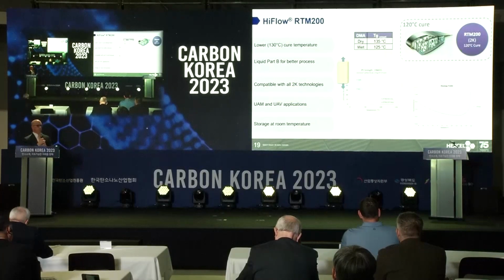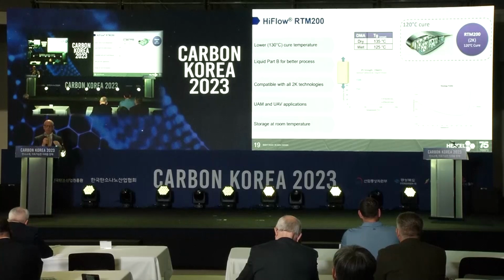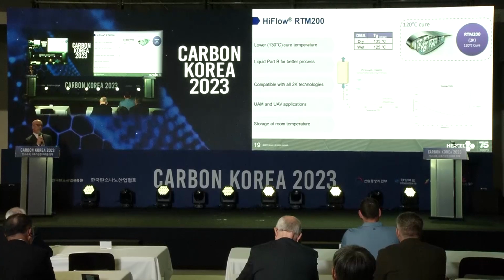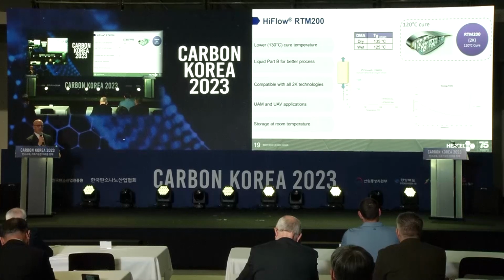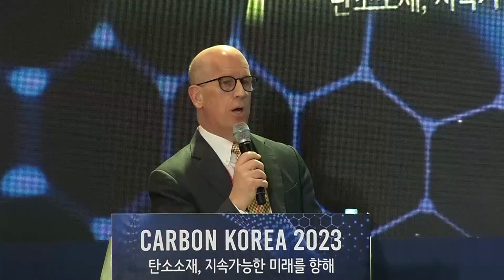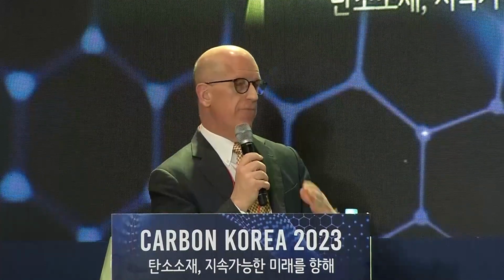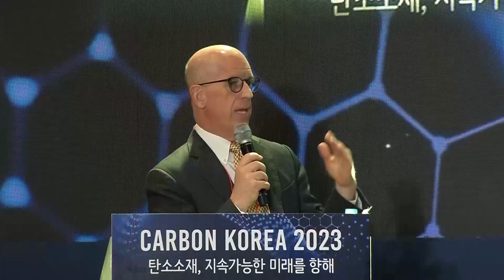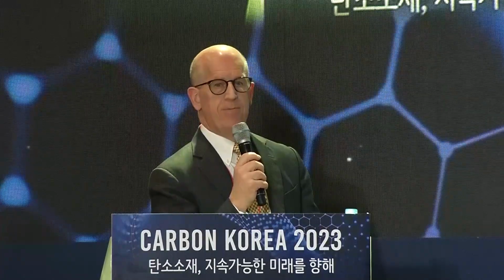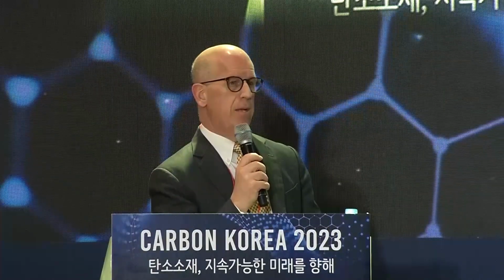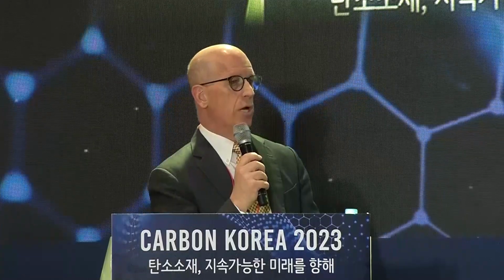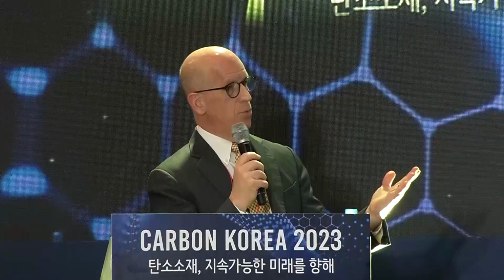And then the RTM 200, as mentioned, we had gotten a lot of requests from the industry to say, hey, your typical RTM 6 has a 350F cure, and that requires us to go to very expensive tooling. If we could get down to a 250F cure system, then we could go to lower cost tooling, and that would allow us to really reduce the price and increase the rate. So we came up with the RTM 200.